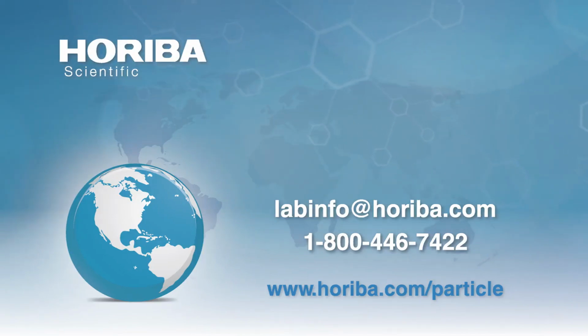But you apply sonication, and then you look at the particle size as a function of total specific energy that you put into that. And you will often see plateaus where you can kind of figure out where bonds are breaking, things like that. So careful analysis requires a lot of time. I mean, that's the trick. But first you have to define what you want. When you say agglomeration, you want to know the aggregates that are making up the agglomerates, or you want to know something else?